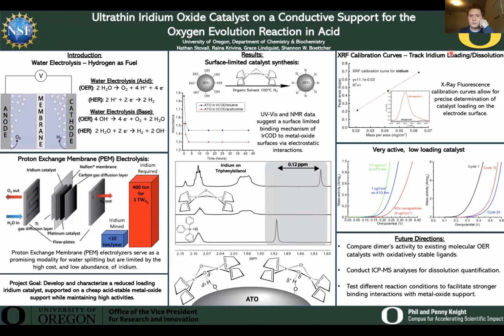And next, we wanted to develop a calibration curve that allows us to track the loading of our catalyst on the surface of our electrodes before running electrochemical measurements. To do this, we were able to use X-ray fluorescence and relate the peak area of X-ray fluorescence data to a known mass of iridium that we were able to calculate using a quartz crystal microbalance on a quartz crystal. And as you see, you get a linear relationship, which then, as we build our electrodes, will allow us to determine the mass loading on that electrode and therefore compare catalysts between each other as a function of their mass.